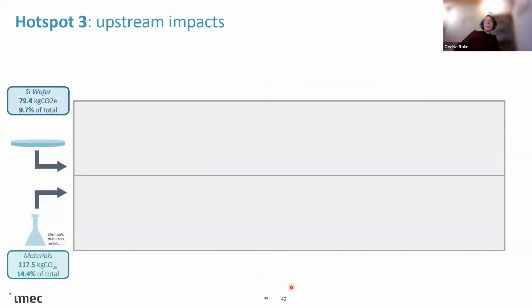A third hotspot is actually related to the climate impact of the upstream materials. So here, this is not an impact that directly comes from the fab itself or from the energy that the fab is using, but rather from the supply of the materials used by the fab. So it's very often referred to as being a scope 3 impact of the fab. And for example, in the data I already showed, the total impact of this material supply is estimated to be about 15% of the total. And actually, one of the big components of this impact is related to the supply of the silicon wafer. That is really the starting point of semiconductor manufacturing.